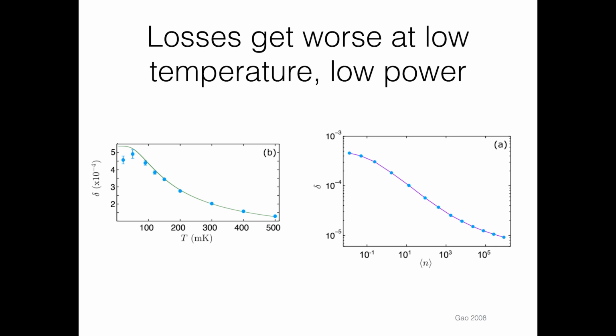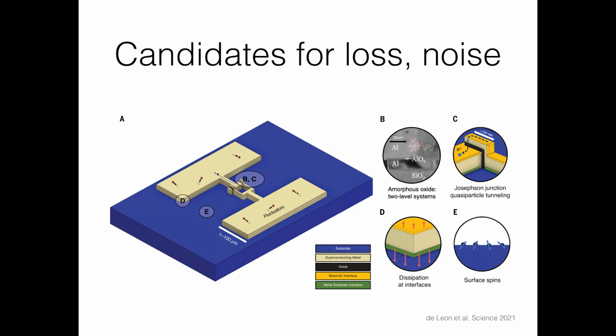And all of these things sort of point to, I have something that can saturate. So I have something that causes loss that if I drive it hard enough, I make that loss go away. And this is why in this literature, you hear a lot of people talk about so-called two-level systems, because two-level systems are things that intrinsically saturate by definition. All right, so we're looking for things at surfaces and interfaces that could be like two-level systems. And I can just stare at one of these devices and say, okay, there's a boatload of interfaces and surfaces here. Maybe I can figure out which surfaces are actually responsible for the loss and come up with a playbook for systematically characterizing and categorizing this loss.